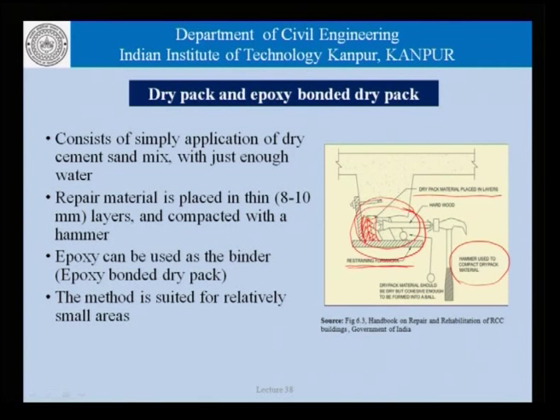Instead of a cement based binder, we could also use an epoxy based binder, in which case what we would call this method is epoxy bonded dry pack, and the method is obviously suitable only for small areas and susceptible to changes in the quality of the work done depending on the workman involved, because all the operations are strictly manual. The mixing, perhaps, the compaction is completely manual, and so on.